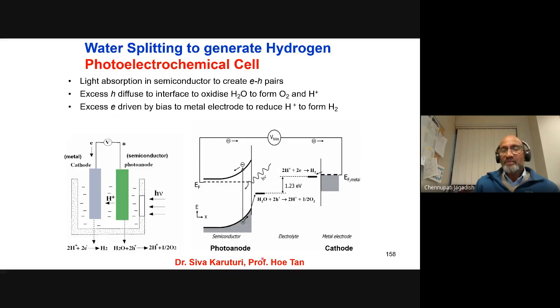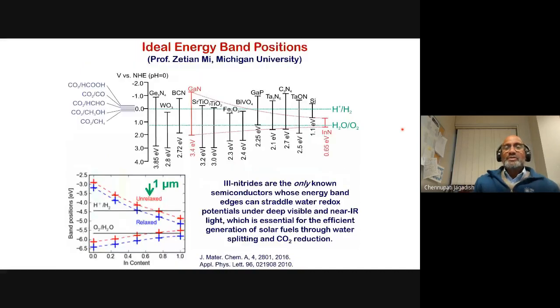And again, this work is led by my colleagues, Dr. Shiva Karaturi and Professor Hotan, for example. In fact, we've looked at a wide variety of materials. This is a slide which I borrowed from Professor Zetian Mi from Michigan University. They've looked at a wide variety of materials, and typically chemists end up using titanium dioxide. One of the requirements is that there's a conduction band and a valence band, and the band gap of this semiconductor is such that the redox potentials of water should be in the middle of the band gap here.